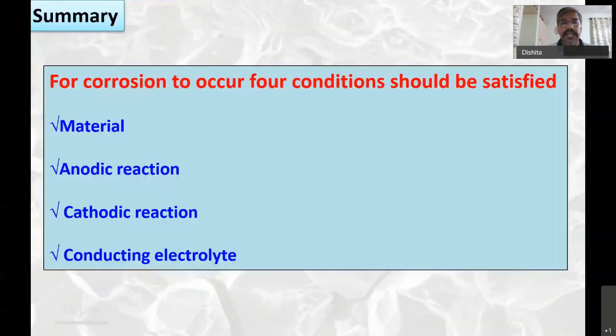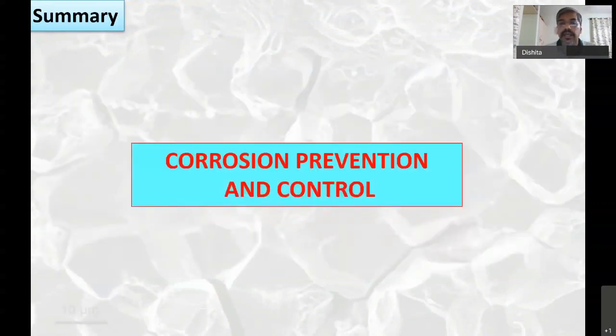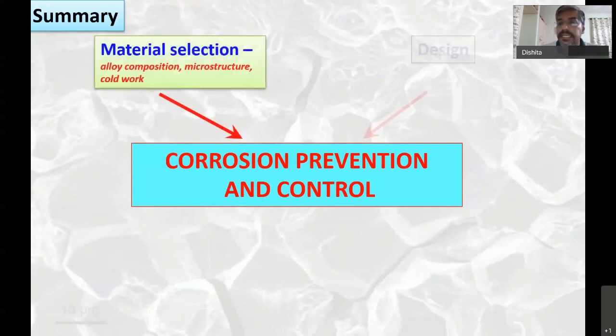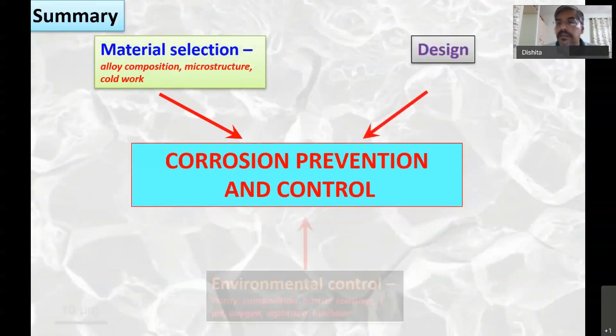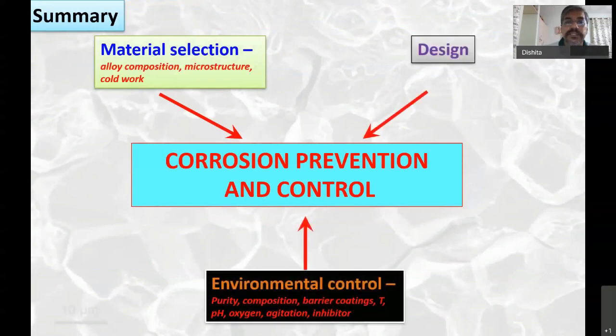So finally, to summarize, for corrosion to occur you need four factors: material, an anodic reaction, a cathodic reaction, and a conducting electrolyte. You can prevent and control corrosion by proper material selection, taking care of alloy composition, microstructure, cold work, and taking adequate steps during design. These two steps can be taken before the material goes into service, and during service you can control the environment by purity, minimizing the concentration of corrosive species, composition of the environment, barrier coatings, temperature, pH, oxygen, agitation, and addition of inhibitors to the environment. All of them will control your corrosion.